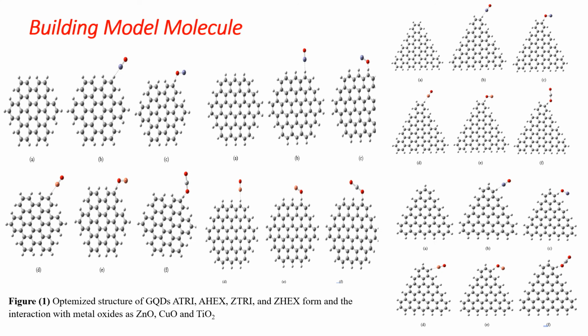To study the effect of decorating graphene quantum dots with metal oxides, we built our models as graphene quantum dots with different shapes, hexagonal and triangular, with 2 forms, zigzag and armchair, interacted with metal oxides such as zinc oxide, copper oxide and titanium dioxide, once from the oxygen atom and once from the metal atom. All model structures were used to calculate the HOMO-LUMO bandgap energy and molecular electrostatic potential to study their electronic properties.